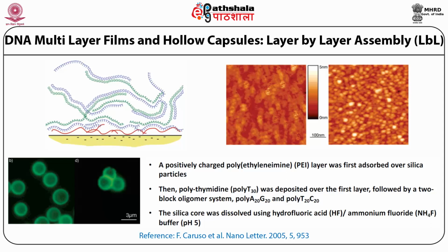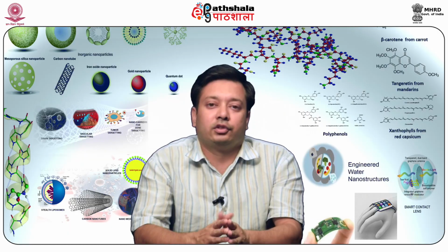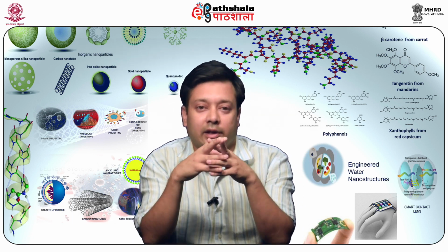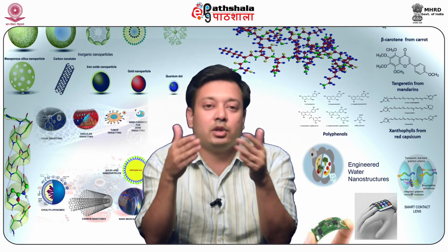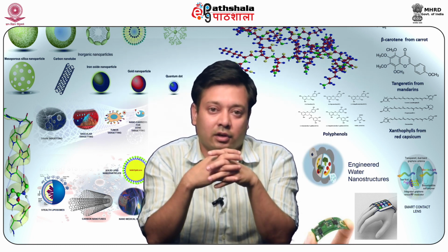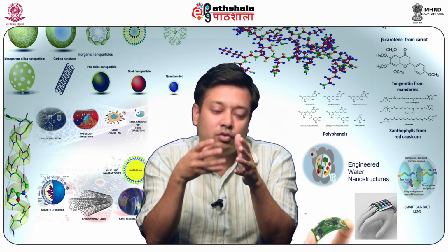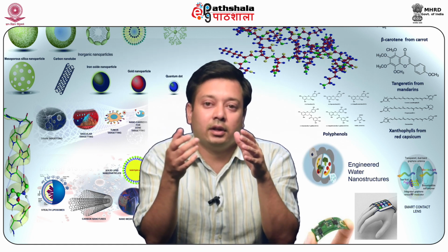Now when you put this kind of layer-by-layer self-assembly on a silica particle, and then you dissolve the silica particle using hydrofluoric acid or ammonium fluoride, then you can actually create a hollow capsule which can be used as a nanocontainer. So inorganic nanostructures like gold nanoparticles, silver nanoparticles, or mesoporous silica nanoparticles can all be used for drug delivery application. Gold nanoparticles, as I said, can be used for drug delivery and sensing application,